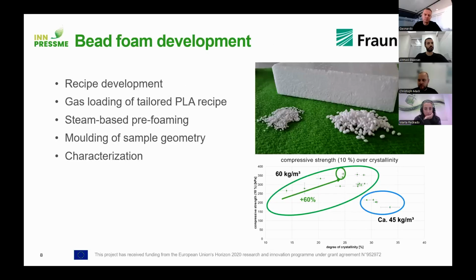Coming to the bead foam development, which took place mostly at Fraunhofer ICT, we developed a special recipe made from PLA. We loaded this recipe with gas to receive expandable granules. Those were then pre-foamed and molded to a sample geometry, and then we did the characterization. And this was done several times, of course, in an iterative way to improve the properties.